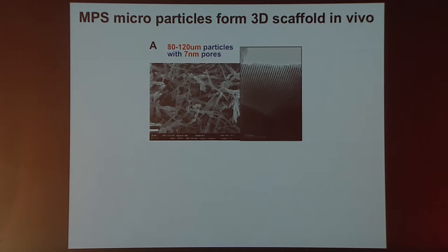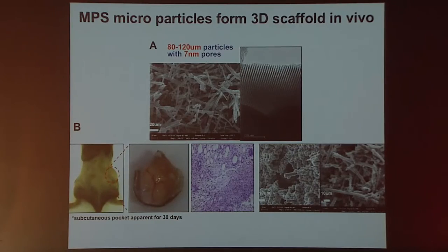The approach uses mesoporous silica — a type of silica that is nanoporous, as seen in TEM analysis, with pores on the nanoscale into which we load the biologics. When injected into mice, they generate a small pocket; explantation reveals a nodule of tissue. Under EM, you see a highly cellular site has formed. If we digest away all the cells, you can appreciate all the microparticles that assembled together to form a porous structure in situ, to which cells were recruited.